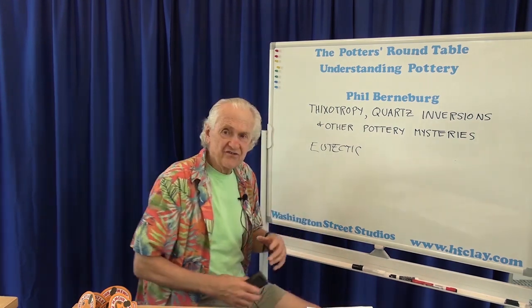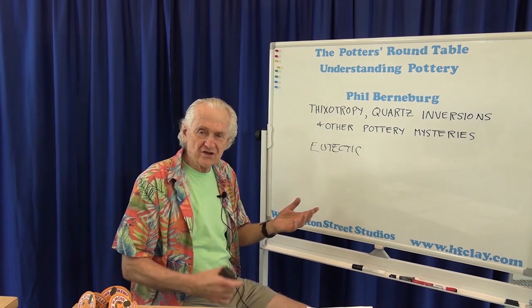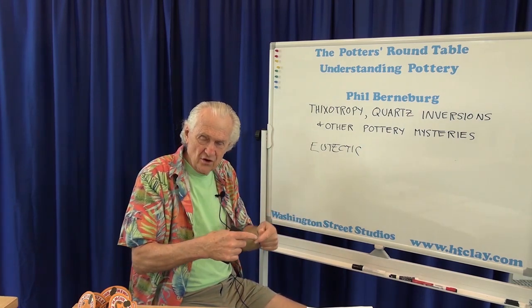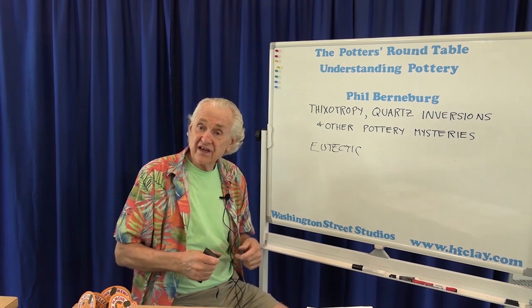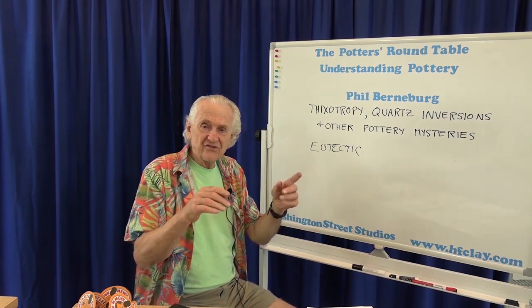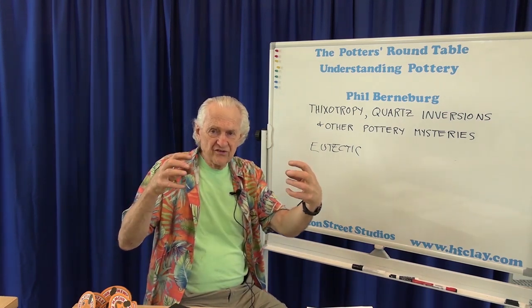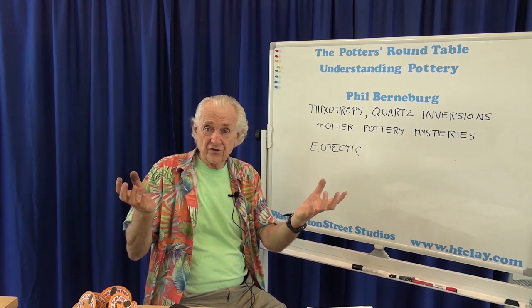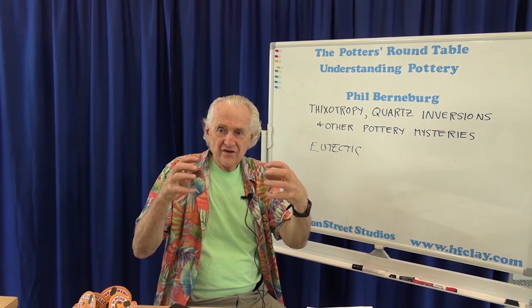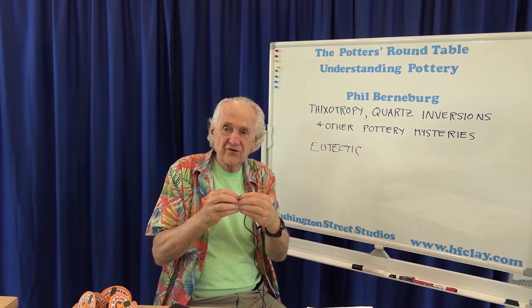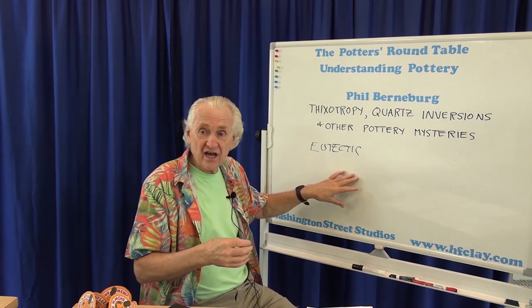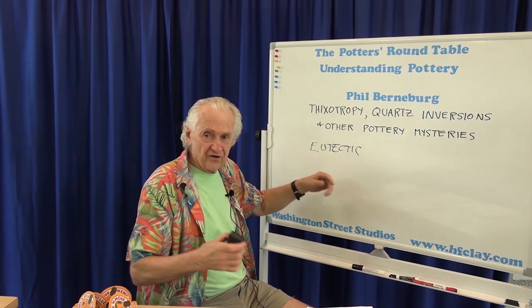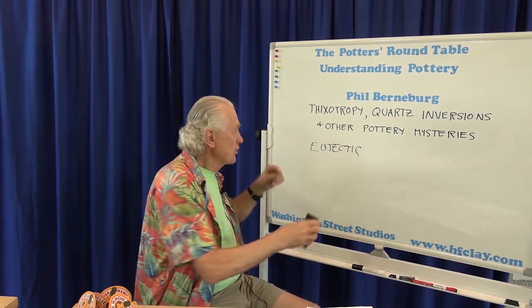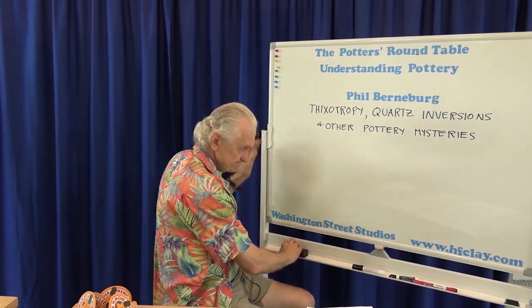Okay, and so you talk about the eutectic temperature, that's the temperature at which this lower melting occurs, or the eutectic composition. That means that there might be certain proportions of two materials, and this is true for the ice and the salt. There are actually certain proportions where this eutectic happens and you get the lowest temperature, and that's called the eutectic composition. But it all refers to this formation of this lower melting temperature.